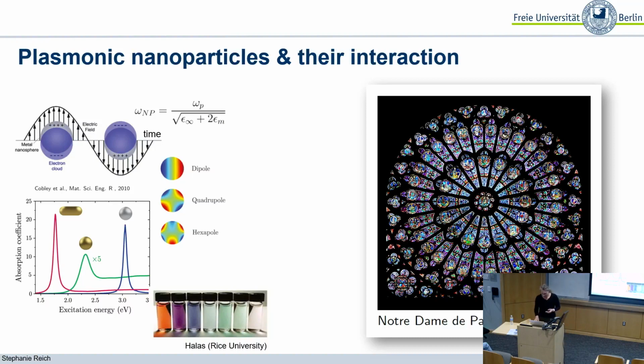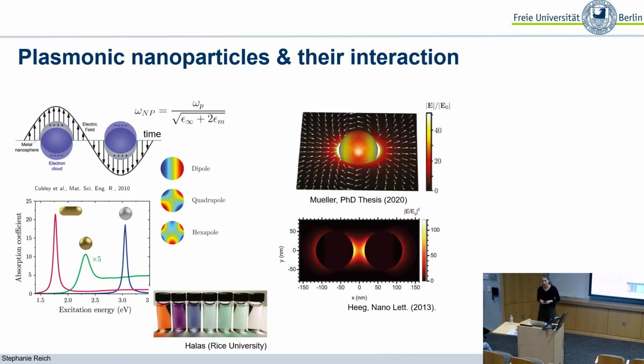One of the key features of these metal nanoparticles is that if you excite a plasmon in such a metal nanostructure, it will produce a very strong optical near field close to the metal surface. This is a simulation where you plot the E field intensity relative to the intensity of the incoming light used to excite the plasmon resonance, and you can see an enhancement of an order of magnitude at least. Then you can combine two of these nanoparticles, and if you shift them close enough together so that the electric fields overlap, you get an excitation that has a very strong hotspot in the middle.